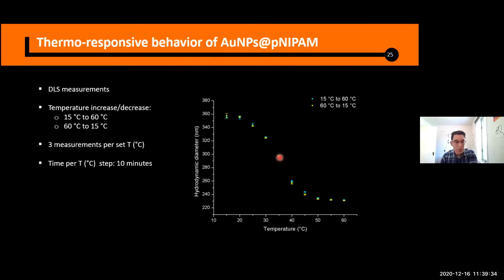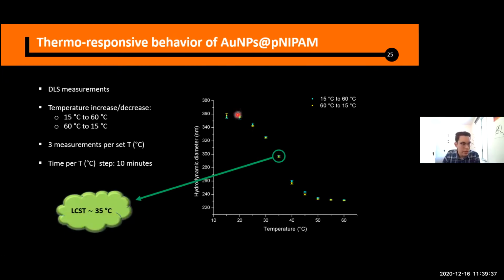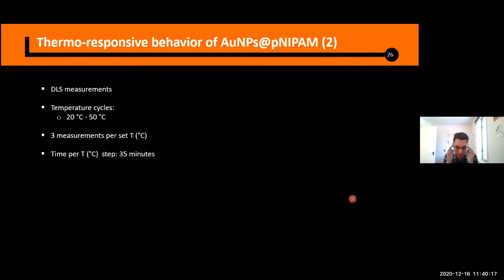At temperatures lower than 35 degrees Celsius, we say that the particles are in their swollen state, so they are full of water, like a sponge. And then when we start increasing the temperature, the water starts to be released because the polymer is shrinking. And here we can see that going from 15 to 60 and from 60 to 15, this behavior is quite the same.